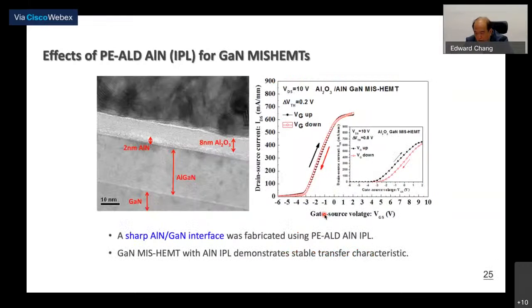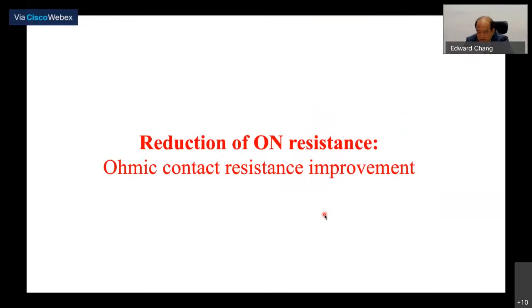And this is the one we use, aluminum nitride plus aluminum oxide, okay. You can see in the layer, 2 nanometer aluminum nitride and aluminum oxide, you can get very small hysteresis, and also the current collapse is very minimized. Okay, and then the reduction of ohmic resistance, you can improve the ohmic contact resistance, okay.